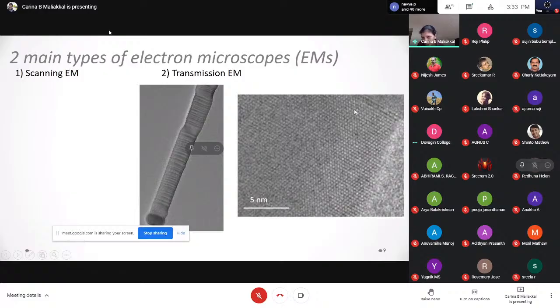So you see these dot-like things, and the black portions in between are basically the atomic columns that you're seeing. You can resolve with an electron microscope even to a level of a few atoms. It's actually a whole column of atoms. Through the entire depth of that sample, you have atoms sitting, but you're looking at it in a nice crystallographic direction so that all the atoms are sitting one behind the other, which is why you don't see a blur, but you actually see atomic columns in this picture.